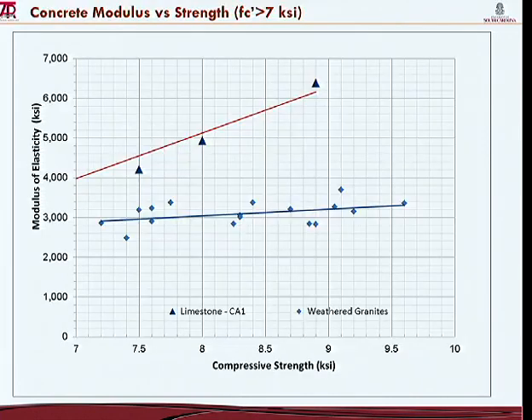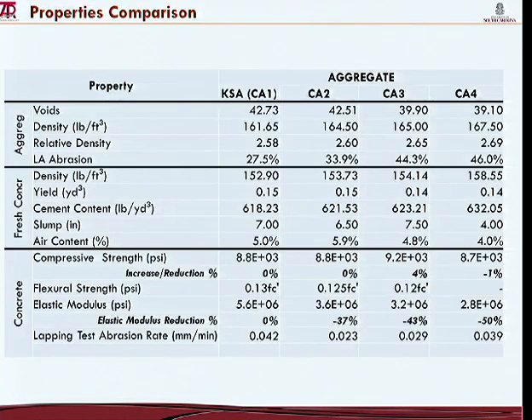And here's a correlation between the modulus and the compressive strength for our baseline, the standard mix, and the weathered granites. These data are plotted for strengths above 7 KSI, which is our minimum design strength for the concrete batch. So taking a look at the properties now, notice that as far as the aggregates are concerned, voids, density, and relative density are all very comparable. In the LA abrasion test, the weathered aggregates showed a higher degree of damage, if you want, of loss.